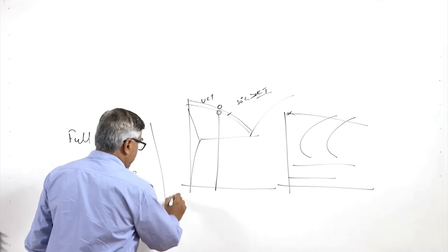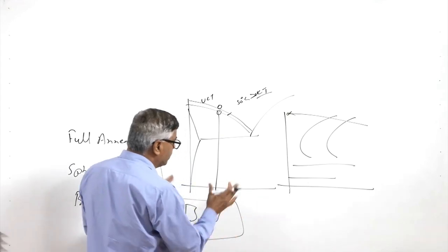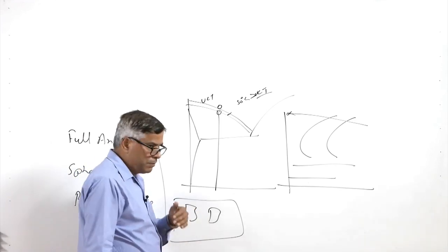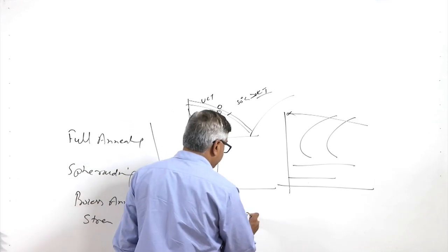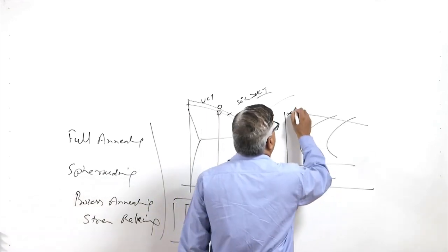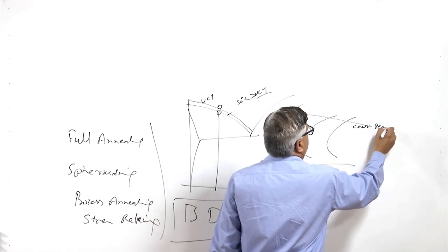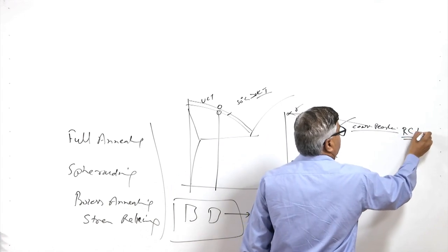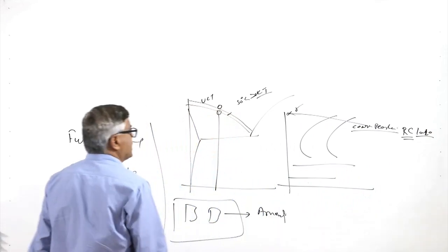So, in the furnace being used for the heat treatment purpose, we heat it. After soaking, the furnace is closed, so that heat loss takes place at a very low rate. The objects to be heat treated will experience the lower cooling rates, and that in turn will lead to the annealing, because for annealing we need very low cooling rates, and when it happens it will lead to the formation of very coarse pearlite. And coarse pearlite results in a very low hardness of 10 to 20 HRC as per the carbon content in the steel.